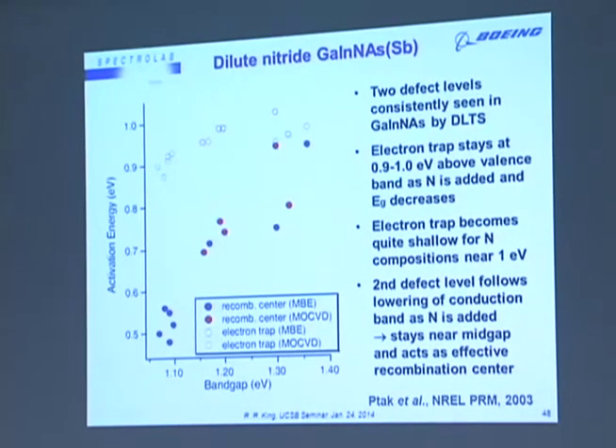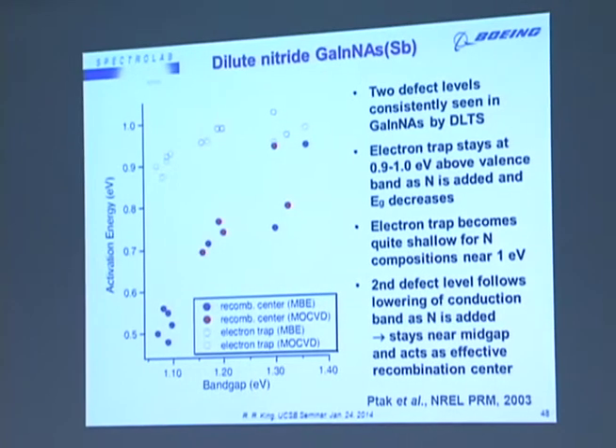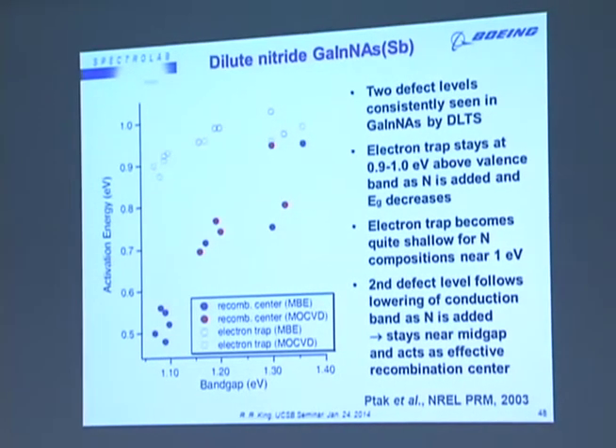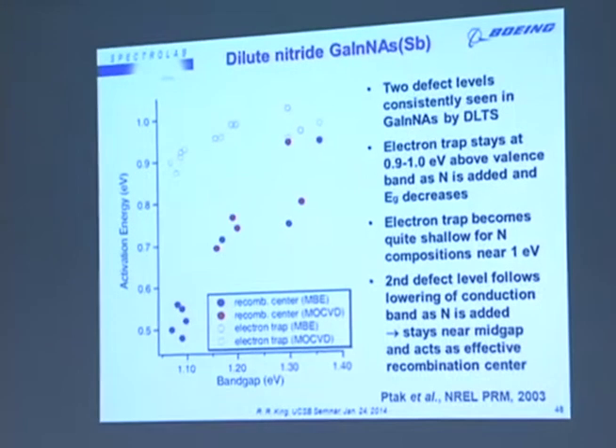One important one is this electron trap, which stays at about 0.9 to 1 eV above the valence band as nitrogen is added and the band gap decreases. So that, unfortunately, becomes more benign. It becomes more shallow near 1 eV. There's a second defect level that follows the lowering of the conduction band and stays near the mid gap, and that's more problematic.